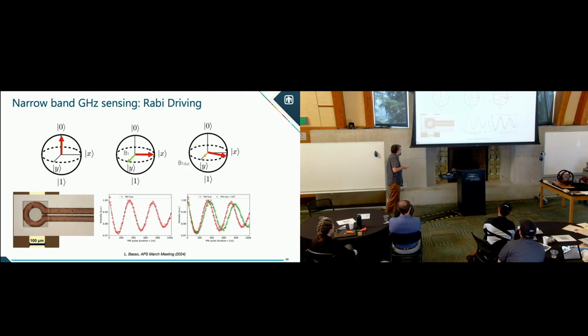Now, we do this with a microwave loop with a diamond on it, but then you can also have some device under test also have a very small AC field on it. This is up to 4 orders of magnitude smaller at the same frequency, and you can see how much that shifts your Rabi drive. In this case, the red was just our microwave loop, and the green is with some device.